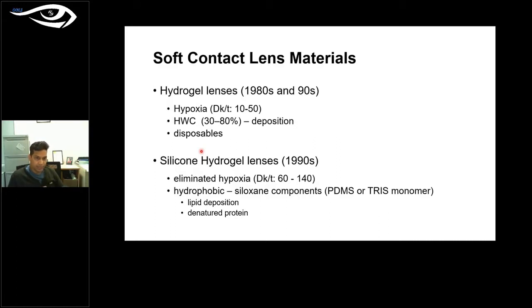Contact lens materials are broadly classified into two categories. One is the hydrogel lenses, which were very popular, and even now they are popular, introduced in the 80s and 90s. One of the major disadvantages with these, even though they were comfortable, was hypoxia. Hypoxia is the main reason because the oxygen reaching the corneal surface through the contact lens material was relatively poor. One way to increase oxygen permeability of the material was to increase water content. But there was an issue. As you increase the water content, there are other issues such as lens deposition. And one way this deposition problem was solved was by introducing disposable contact lenses.